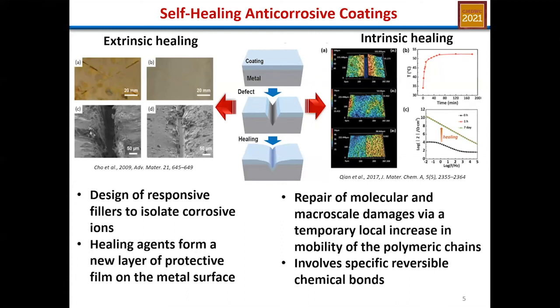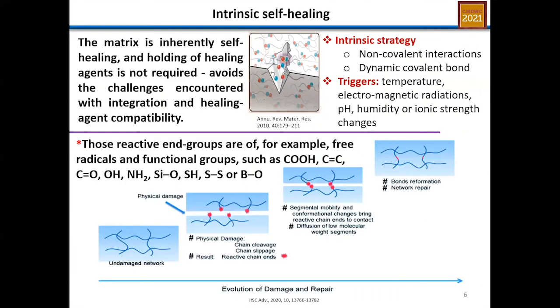But when you talk about the intrinsic healing, we're looking at mobility of the polymeric chains itself, and possibly this involves specific reversible chemical bonds. So for the intrinsic healing, it's the matrix that is actually involved, and this avoids the challenges of integration or compatibility of external healing agents. And the reactions are mostly non-covalent or dynamic covalent bonds. The common triggers are temperature, electromagnetic radiation such as UV rays, pH, humidity, or ionic strength changes. So when you talk about the intrinsic healing, we're looking at those reactive end groups that will be able to form cleavages through segmental mobility when there is a physical damage, and that produces a bond reformation and repair.